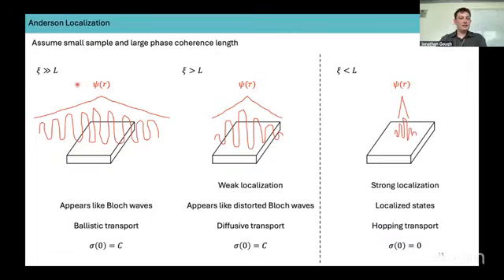So now if we take this relatively simple example, so we assume we've got a very small sample here, and also we're at low temperatures, so the phase coherence length is very large. So we're increasing disorder from left to right. So at very low disorder, the localization length is much bigger than the sample size. So over the sample, it just appears like standard Bloch waves, as you may be familiar with from undergraduate physics. So transport's most likely ballistic, and as the wave function extends throughout the sample, it behaves like a metal. The zero temperature conductivity is a constant.